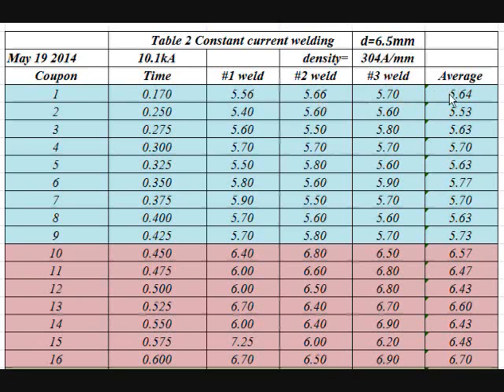We got an average of 5.64, which is approximately 1 millimeter less than the diameter of the electrodes. And this goes on for 9 coupons, and from 170 to 425 we are getting more or less identical size nugget. From 9 to 10 we only increased 25 milliseconds, and all of a sudden the nugget size jumped from 5.7 to 6.5.